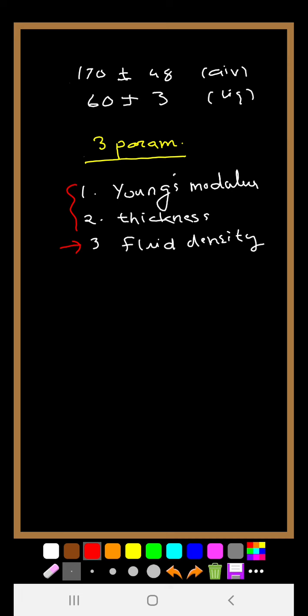Now, the Young's modulus of silicon varies in different directions in the material relative to the crystal orientation, and usually we take silicon 100, which is assumed to have a modulus of 169 GPa in the direction parallel to the flat.